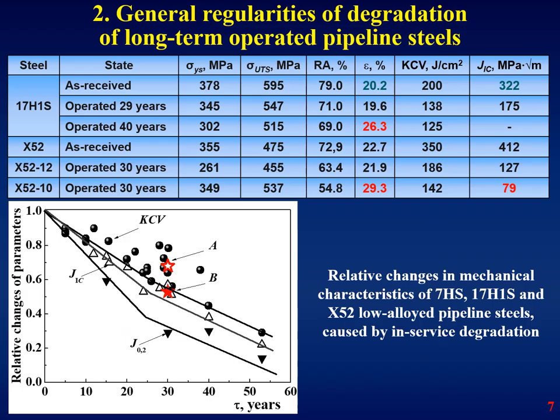General regularities of degradation of long-term operated pipeline steels: the main peculiarities of operational steel degradation consist in decreases of plasticity and brittle fracture resistance, such as impact strength and fracture toughness. On this slide you can see a figure with the relative change of these parameters during long-term service. Fracture toughness defined by the J-integral is more sensitive to degradation than impact strength, but sensitivity of impact strength can be increased if using the part of this parameter namely energy for crack propagation — that is, crack growth resistance.